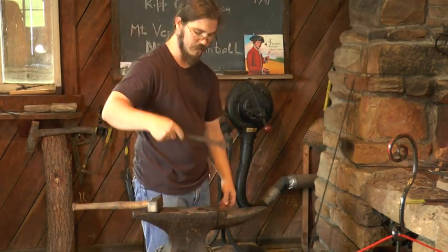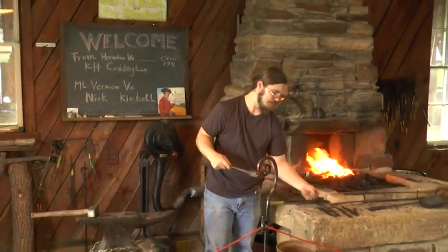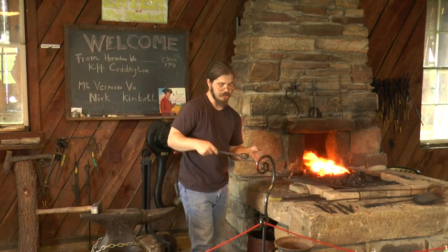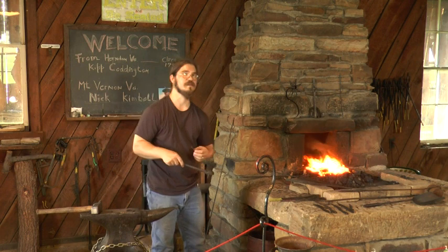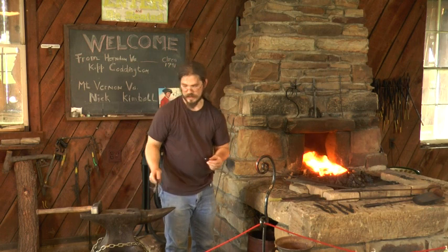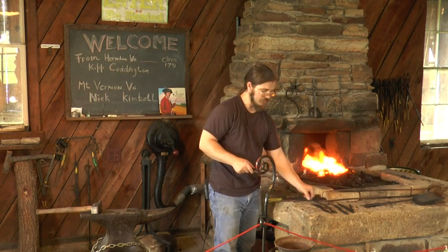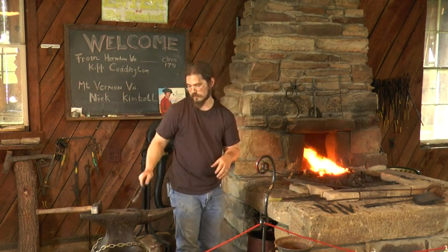That's not too bad. Under a minute. Now the first one I cooled down, you'll typically see people do that, cool down the nails. Sometimes it's to get it out of the nail header. As the metal is heated, it actually expands. You put it down into the nail header, sometimes it gets stuck. So you put it down in there, quench it, shrinks it, and you can just knock it out. I tend not to quench my nails, as that can actually have more negative reactions with the metal than positive. If you have a good even temper and you head the nail while it's still hot, it tends to come out pretty easily.